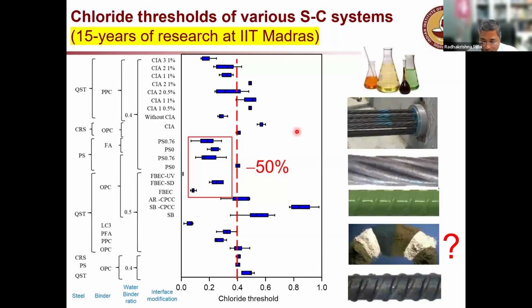Now, I was talking about the chloride threshold. So here we have done a significant amount of study in looking at how these different chemicals and mineral admixtures or SCMs will influence the chloride threshold, and also in particular the chloride threshold of pre-stressed concrete. That is also something which we looked at. And you can look at this graph and see that it is not 0.4. This vertical red line is showing the conventional value of 0.4, whereas we found that it need not be 0.4, it could be less than, more than, all that. There's significant variation in the chloride threshold.